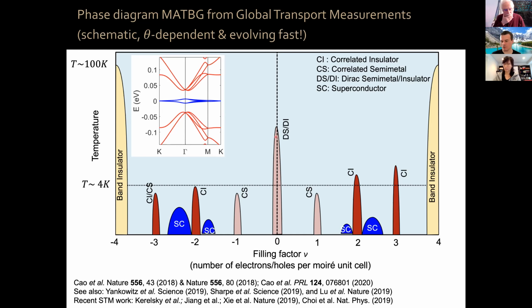And what we saw in transport through several studies, this is just schematic, details can vary depending on the twist angle, etc. But roughly what we see is that features appear at each integer number of electrons or holes per Moiré unit cell. In particular, at 4 electrons or 4 holes per Moiré unit cell, you have either completely emptied this band or completely occupied this band, so you have single particle band insulators. But then, as I mentioned, at other integer filling factors, you have correlated insulator states, which cannot be explained by single particle physics, because your chemical potential is there in the middle of a band. Now, you also have some correlated semi-metal states at other integers.